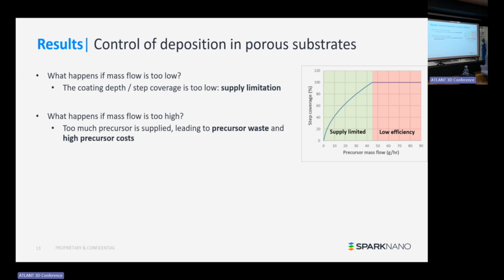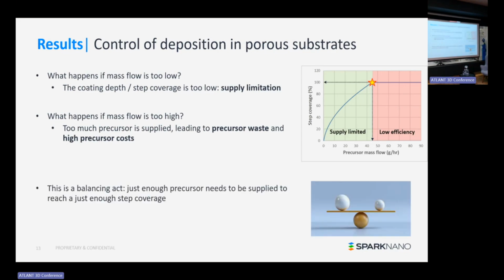You can also have too high precursor mass flow. This means that of course, you cannot go deeper than the pore is deep, so you're wasting precursor. And precursors can be expensive, especially when we talk about iridium and platinum. So you really do want to avoid wasting precursors as much as possible. What you want to do is reach this golden point where you supply just enough precursor to just reach the required step coverage that you need to achieve. And that's why this modeling is so important, because we can actually calculate how much precursor we need to supply. Of course, this is a balancing act. Just enough precursor needs to be supplied to reach just high enough step coverage.